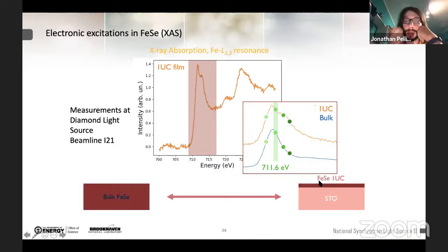And I'm showing in this panel the X-ray absorption spectrum for the two of them. And what we can observe is that there is an extra shoulder on the one unit cell film here, which is compatible with the fact that we have electron doping from the substrate. And it might also be indicative of what I've shown you before on the evolution of the Fermi surface.